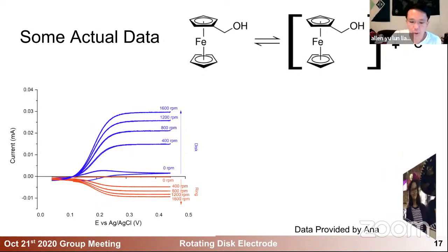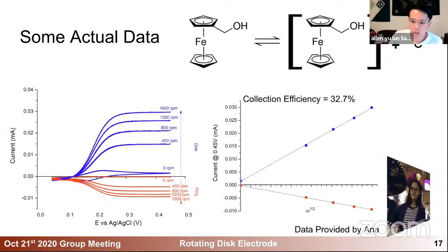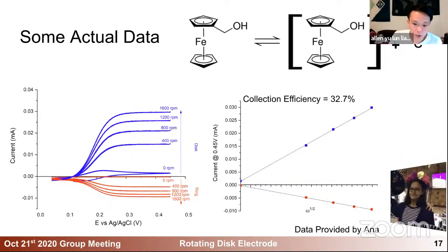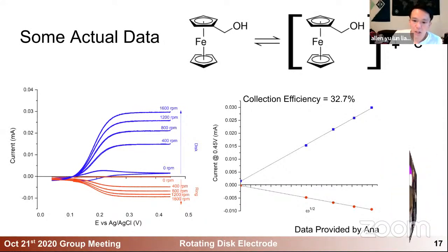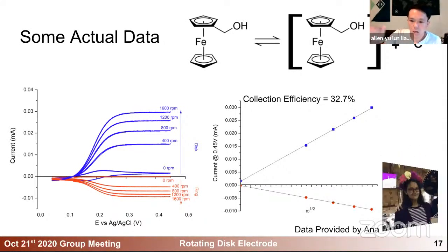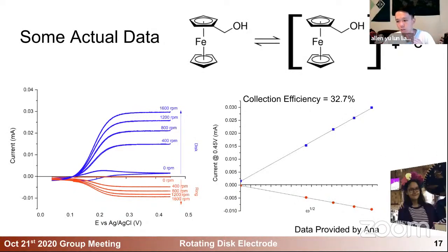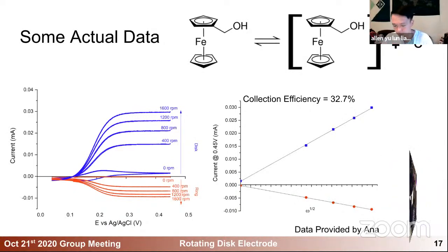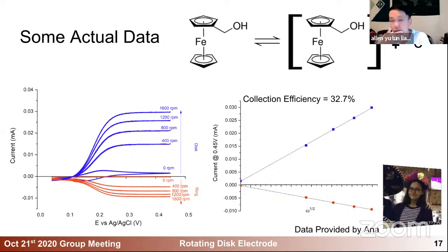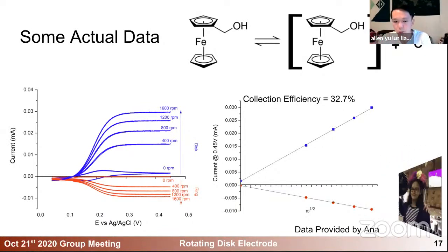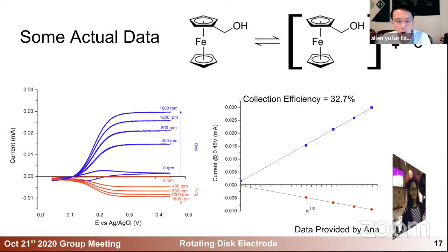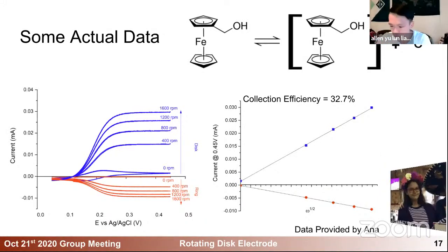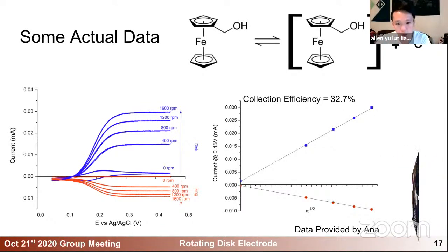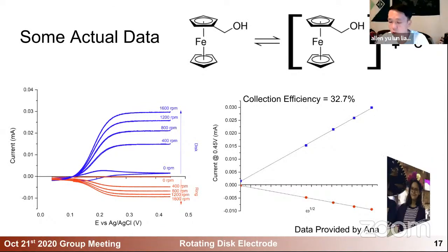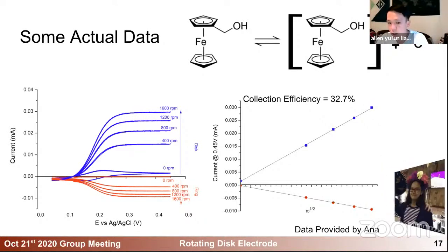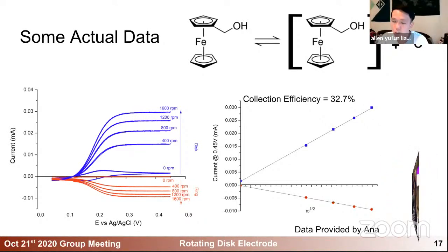And in fact, if you plot this against the square root of the rotating speed, you will see that they all fall onto a really nice line, and then you divide the slope on the ring by the slope on the disk, and you will get a collection efficiency right around 32.7 percent, which is pretty good. I see a lot of literature saying the collection efficiency usually falls between about 20 to 30-something percent, and that's usually just because of the design of your RRDE.